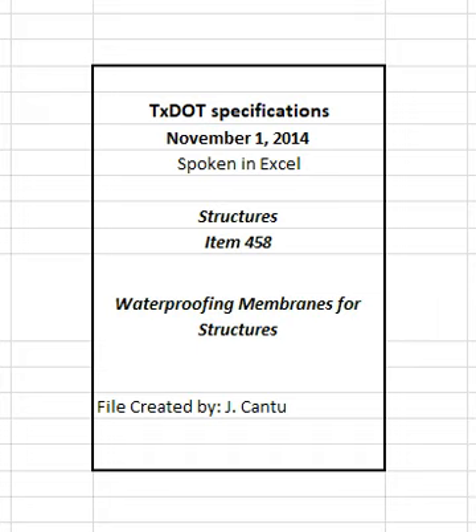3.4 Type 3. Place the asphalt primer at least 24 hours before the asphalt mopping. Ensure the primer is dry before the mopping. Work in the primer to give a uniform coating. Heat the asphalt for mopping in kettles equipped with armored thermometers, but do not heat above 350 degrees Fahrenheit. Stir the asphalt frequently while heating.